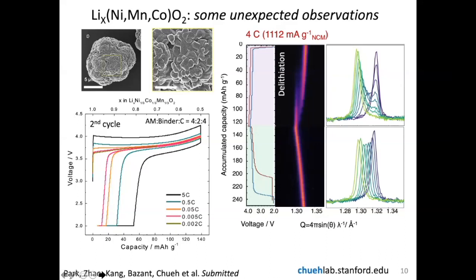And you only see it on charging, but you don't see it on discharging. So this is a very unusual observation because, one, the material is a solid solution. And two, you are seeing this very asymmetric behavior where this phase separation, or what appears to be a phase separation, only occurs on delithiation. We're not the first to see this.